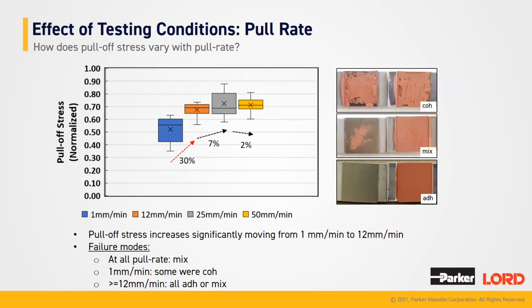Now looking at pull rate, you can see here starting at a slow pull rate of 1 millimeter per minute, there's a lower pull-off stress. But then there is a statistically significant increase from 1 millimeter per minute up to 12 millimeters per minute. And then as you increase pull rates after 12 millimeters per minute, there's a statistically insignificant change up to 50 millimeters per minute. And looking to the right, at the 1 millimeter per minute pull rate, we saw primarily cohesive failure, but then greater than 12 millimeters per minute, it was a combination of mixed and adhesive failure.